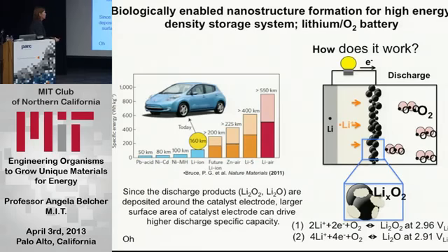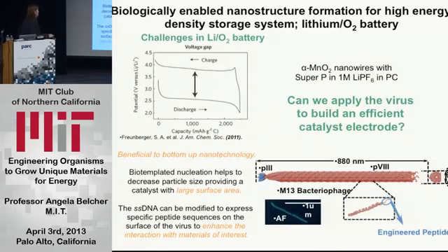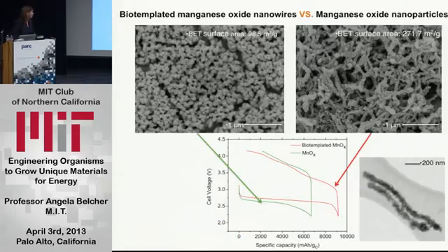And so we decided to go and look to see if we could use M13 viruses to be able to solve this problem, or to be able to think about this problem. And we did the usual kinds of things that we do, and we looked at making manganese oxide nanowires and then incorporating a second material into them. And so we had our viruses and worked out the ability to make manganese oxide nanowires for lithium-air batteries at room temperature. And one of the things we wanted to do was to provide a larger surface area for this catalyst, and to be able to simultaneously have a larger surface area and enhance the interaction of the material of interest in this system. And so I'm showing this actually for the first time, and my student is showing it at MRS tomorrow for the first time.